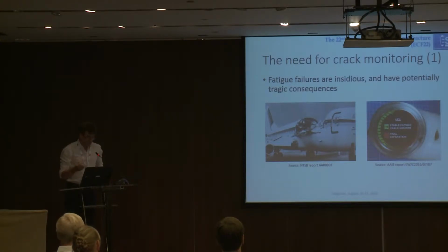It's a pity because I don't remember the author that used that word, but I find it the most appropriate to describe the consequences of fatigue failures, namely that they are insidious. That means that they can occur without any warning that there is a problem, which is of course not very nice, and they have potentially tragic consequences. To illustrate this, I've taken the well-known pictures, which I've seen quite a lot of times at this conference, of the Aloha 737, where part of the fuselage simply detached during flight, and it was indeed due to fatigue crack growth.